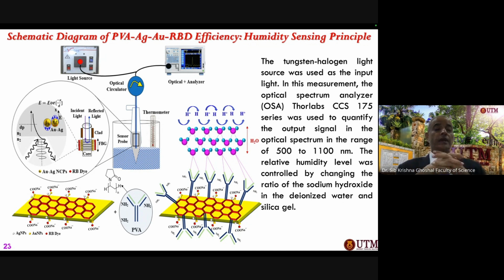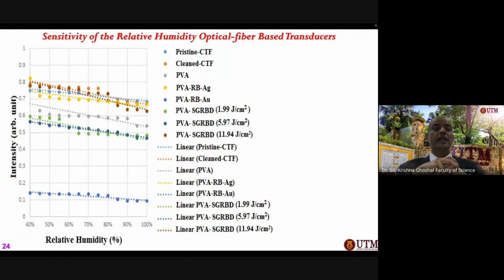So we therefore make a kind of core shell nanostructure so that we can exploit the silver plasmon and we can protect silver from the oxidation process through the gold. So the silver gold core shell nanostructure is very important, and here really intelligent technology is required for the production of the sensing elements. So here is the measurement. When we look at the relative humidity, we use this sensor, then expose it to the varying concentration of humidity. We start with 40% humidity and we go up to 100% humidity.